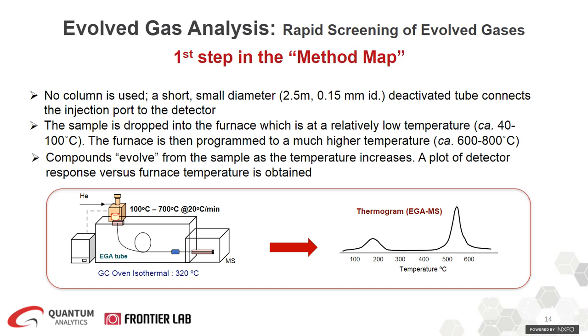So as we mentioned, EGA is the first step. To perform the EGA, as shown here at the bottom in the figure, a short and deactivated tube is used that connects the injection port to the MS. So in this technique, the sample is dropped into the furnace, which is relatively at a low temperature. In this case, we're starting from 100 degrees Celsius.